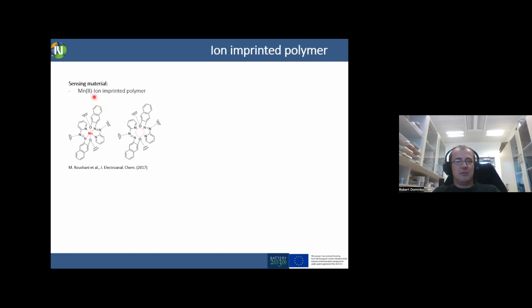an imprinted polymer which can coordinate manganese, and by leaching manganese out, we now have a tool such that if some manganese is dissolved, it will be immediately coordinated by this polymer.